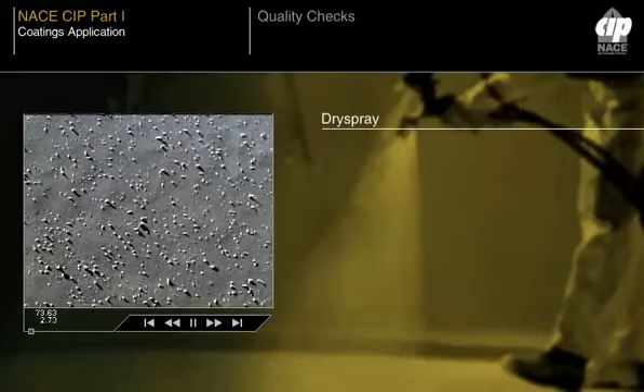Dry spray usually leaves a rough surface, which looks like abrasive dust in the surface of the coating. The dry spray is poorly bonded to the painted surface and may, in some cases, provide sufficient dusting to prevent adequate bonding of the next layer of paint, leading to an adhesion weakness in the system. The problem may be compounded by the entrapment of real dust and other contaminants in the rough surface of the dry spray prior to the next coating operation.